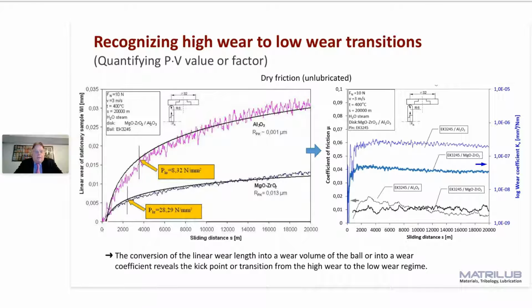And then if you convert those curves, you see that at a certain point the wear rate is constant, and it means from this point onward you are in the low wear regime, because when you start such a pin on disc test with a ball, you have at the beginning high contact stress, you get wear, the surface gets bigger and bigger, and the contact stress goes down automatically. It means when you have a linear wear measurement in a tribometer, you can distinguish if it happens at this point, this critical contact stress where you have the low wear and high wear transition.